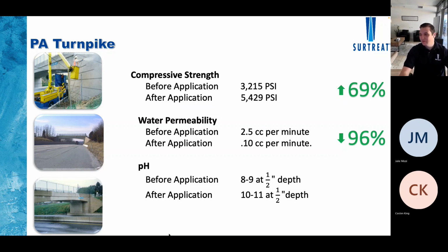So, increasing compressive strength 69%, reducing water permeability 96%. That's porosity. That's the thing that allows the chlorides to come in and damage the concrete. And it increases the pH from 8-9, which is a corrosion active state, to 10.11, which is a corrosion passive state. So basically at that point, rebar cannot corrode.